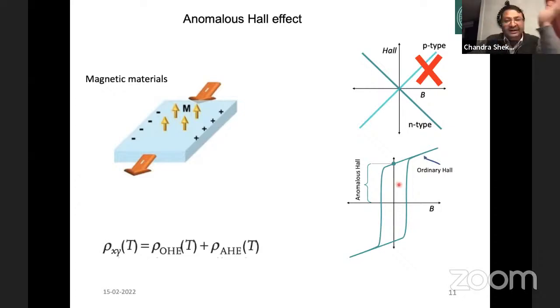But in a non-magnetic material, this Hall voltage or Hall resistance is zero at zero field. When you switch off the magnetic field, it goes to zero in a non-magnetic material in the basic Hall effect. But when you apply the same thing in a magnetic material, it changes the behavior from linear into non-linear. So there are two components inside the magnetic material. We can see this total resistivity, which is called the Hall resistivity, is the combination of ordinary Hall and anomalous Hall. The non-zero part at zero field, we call the anomalous Hall.